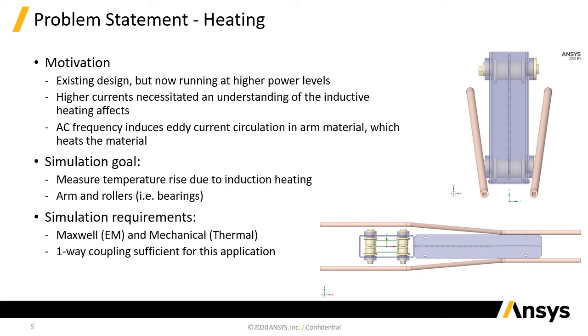So even though we now had an electrode arm design that was more familiar to us, we were going to be operating at higher power levels than we had before, which meant that our understanding of the inductive heating effects was now to be questioned. We did consider completely mitigating those effects by fabricating the electrode arm from austenitic stainless steel. However, at a cost factor of roughly 3 to 1, this quickly became a last resort as opposed to a first option. So in order to guide our decision making, we needed to quantify these heating effects.